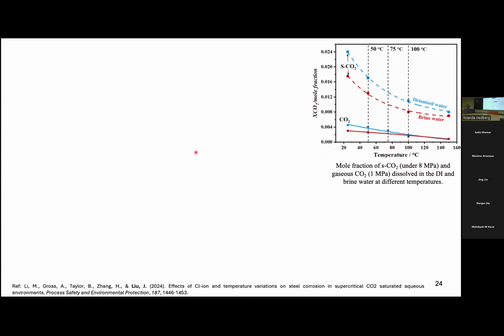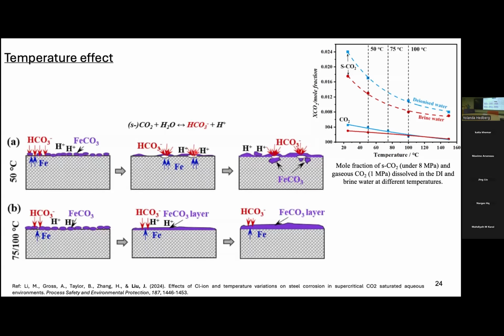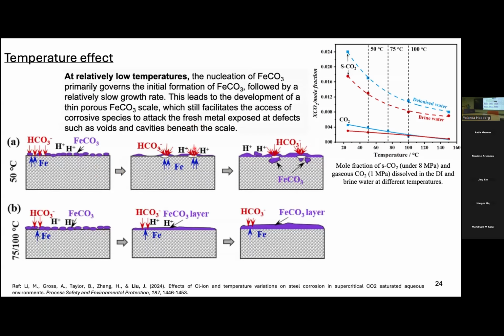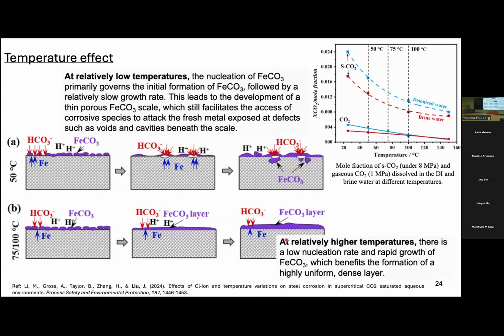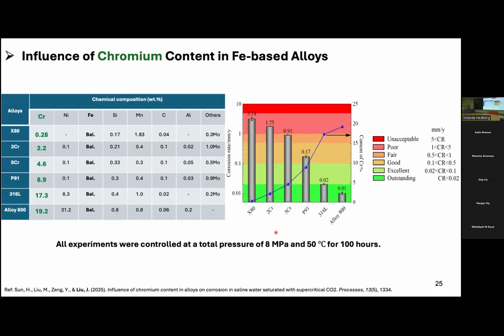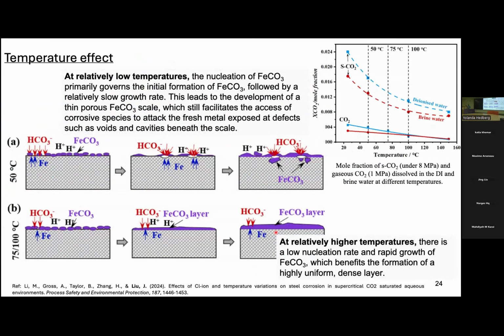And as you can tell, with increased temperature, the solubility of CO2 decreases, so there is less CO2 forming acid in that carbonized water. And at the lower temperature, the nucleation of iron carbonate, the product layer, primarily governs the initial formation, followed by a relatively slow growth rate. So we have those bumpy porous sides. But if you look at the relatively higher temperature, they have a lower nucleation rate, but they grow very fast. So they cover the surface rapidly. So that explains it overall.